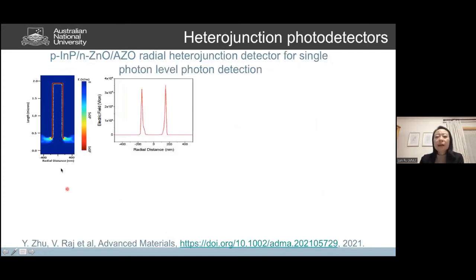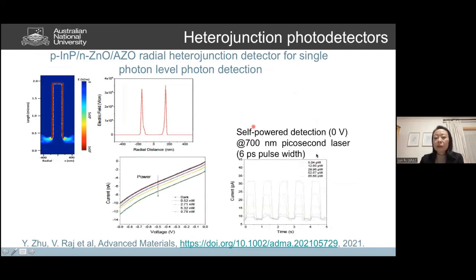Using a similar design, we again use it as a photodetector. What we found is that because of this radial heterojunction formed on the nanowire surface, with a very high field, we can significantly suppress the dark current in this structure. Thereby, we can detect light at the single photon level. So you can see that we're able to detect very weak light, at the nanowatt level, and also operate in self-powered mode.